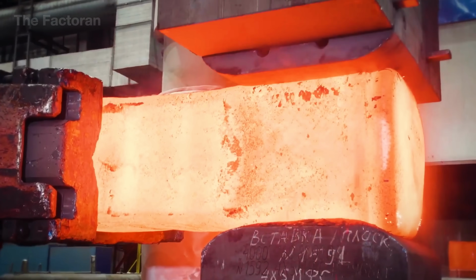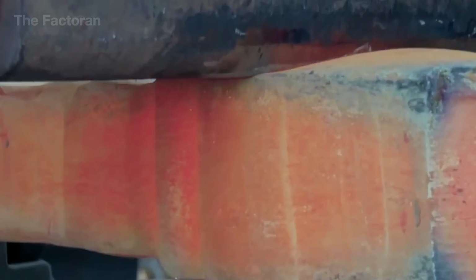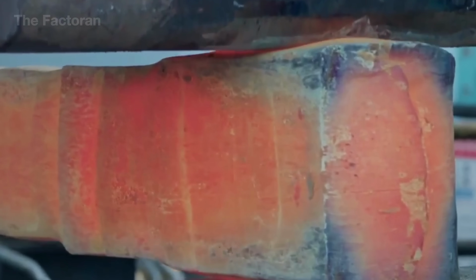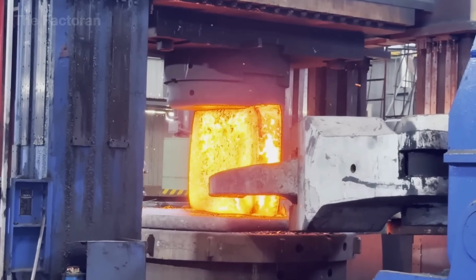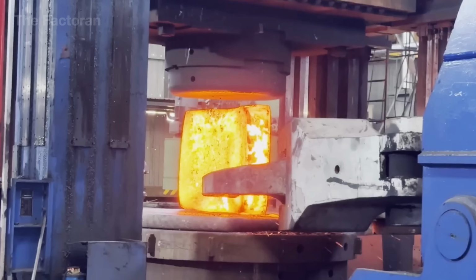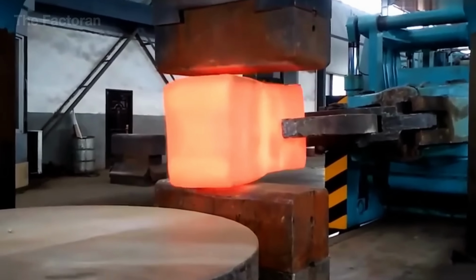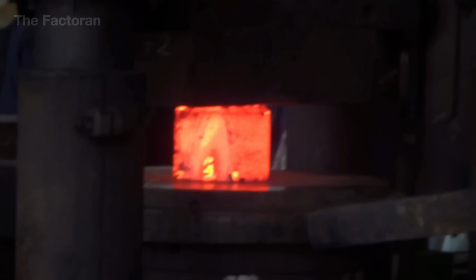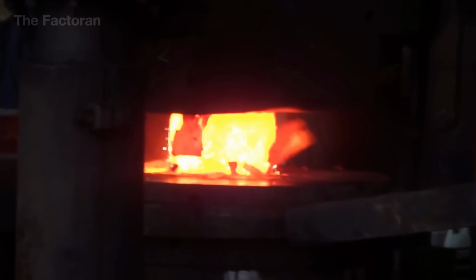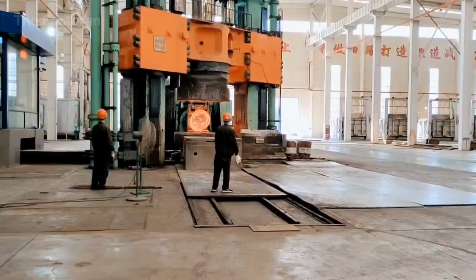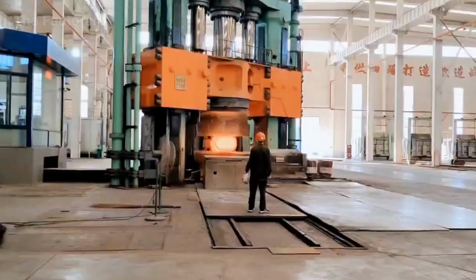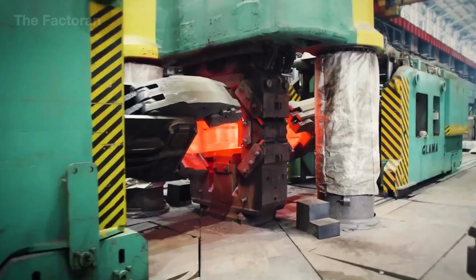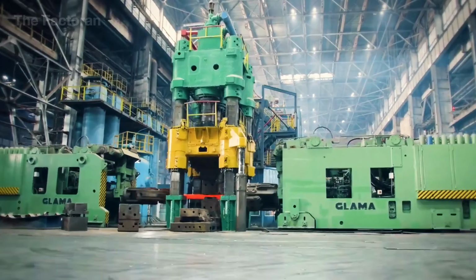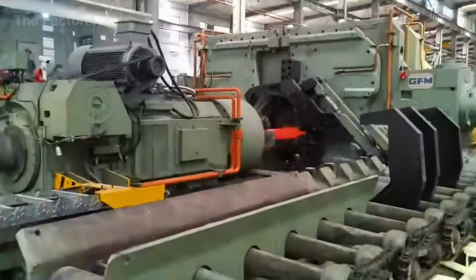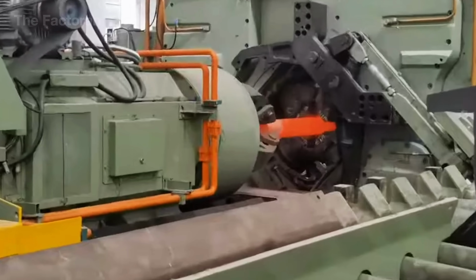Just as important, the forging process densifies the internal structure, eliminating the tiny voids left from casting and realigning the crystalline grains, giving the titanium greater mechanical strength. Through repeated pressing cycles, the glowing ingot gradually becomes a precisely formed billet, consistent in quality and shaped for the next stage of rolling, forging, or precision machining. This marks a pivotal moment when titanium leaves behind its raw cast form and enters its life as a true industrial material.